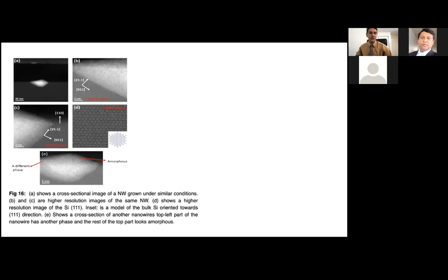There's a special property of this nanowire. You can see that during the formation of the nanowire, part of the nanowire is embedded into the bulk silicon, right? This kind of growth we call endotaxial growth. There are two types of growth for nanostructures: one is endotaxial growth, the other is epitaxial growth, which is formed on the surface. But here, part of the nanowire is embedded into the bulk silicon. We wanted to analyze the crystal structure of the nanowire.